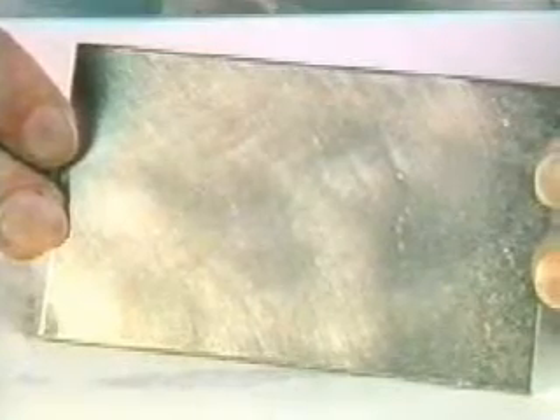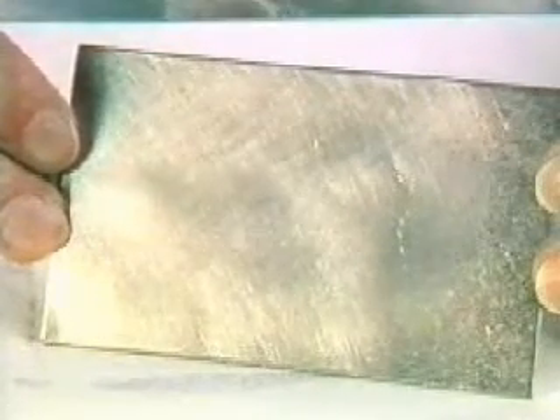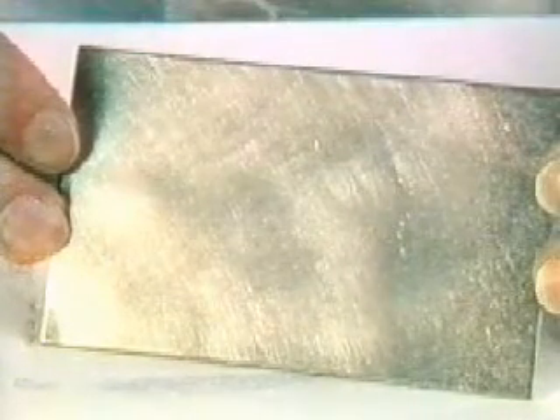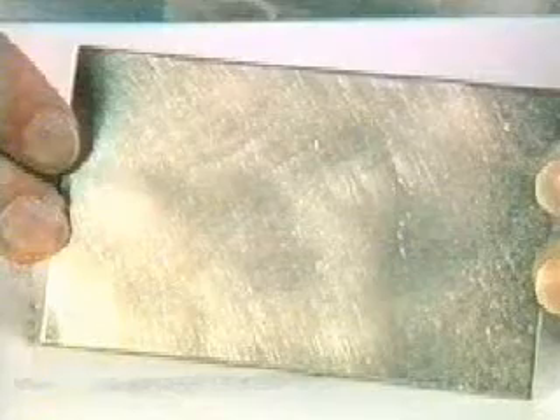The metal dust caused by the roughening is tapped off and the dirty paper removed. The rest of the dust is washed off with pads generously soaked in solvent. The dust must not be just evenly distributed with slightly moistened pads, a practice which is often seen.